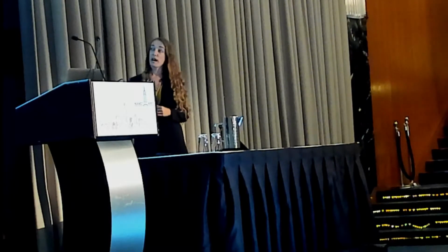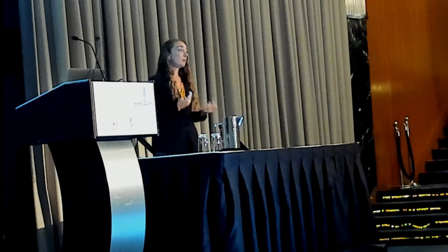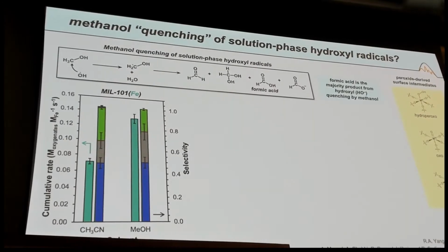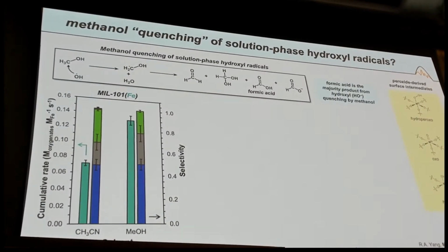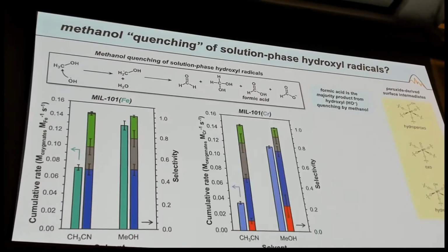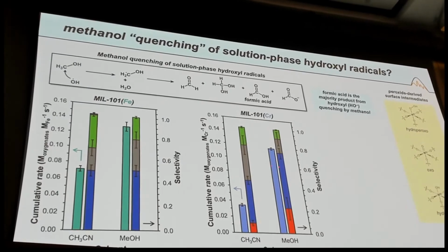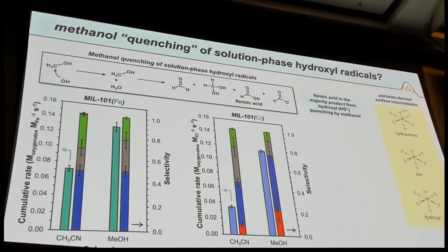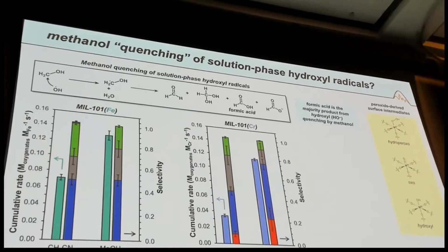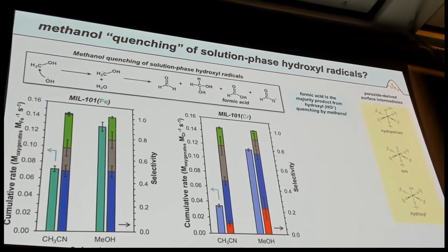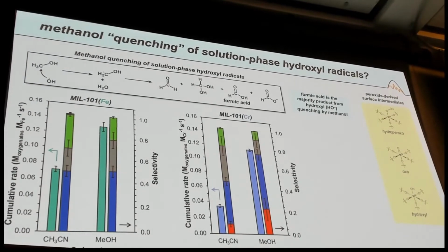However, when we run our reaction for the iron analog in methanol, instead of seeing a suppression of rates, we actually see an increased rate, though we see very similar product distributions, indicative of the fact that we might just have some solvation or some solvent effects, but not really changing relative selectivities of our transition states. However, in the case of chromium, we have both that increase in our rate as well as a slight distribution change within our products. Much more of our products are those primary styrene oxide or the epoxide as well as the benzaldehyde, and much more benzaldehyde by fraction in this case.